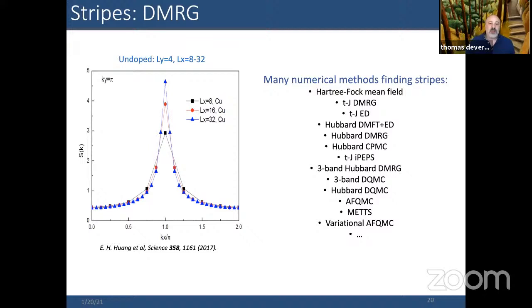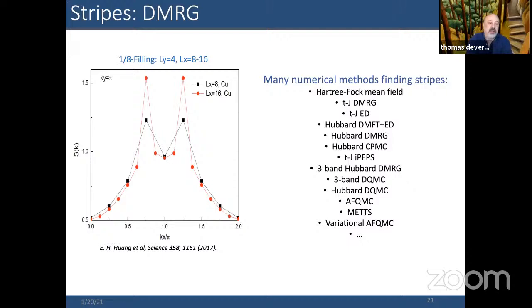Okay, so I'm going to first talk about what I think most people have discussed in this series, which is results from DMRG. There's been a tremendous amount of work where stripes are showing up very clearly, starting from Hartree-Fock mean field, down to variational quantum Monte Carlo and minimally entangled thermal states. The presence of the modulation in the spin structure factor is very clear. Starting from the antiferromagnet, here's three band, the peak in the S of Q splits off of pi to a magnetic incommensurate value, which is set by the doping.